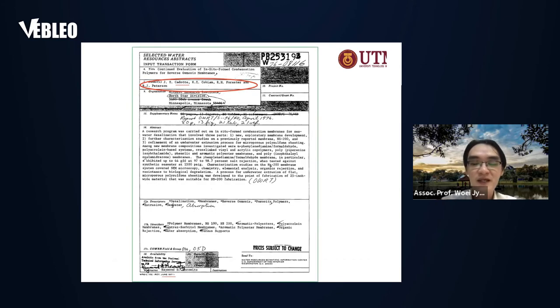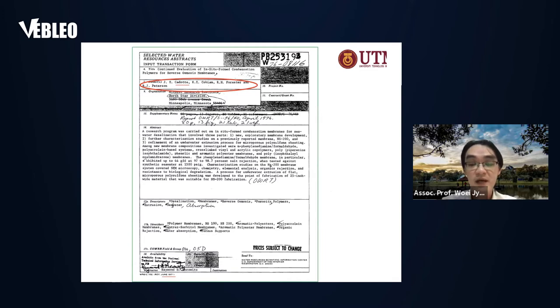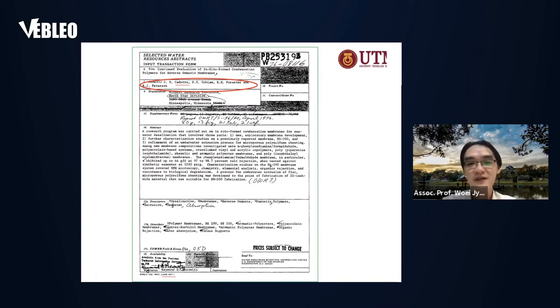It was researchers from the USA — Cadotte and his colleagues — who demonstrated that when you use interfacial polymerization, you are able to form a layer on top of the microporous substrate, and eventually form a membrane with much better flux compared to asymmetric membranes. Because of this research, they were able to commercialize the first reverse osmosis TFC membrane in the 1970s, and then the TFC nanofiltration membrane in the 1980s.